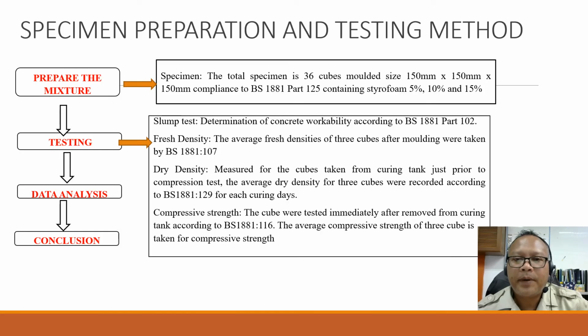Specimen preparation and testing method. For preparing the mixture, the total specimen is 36 cubes, molded at size 150 mm times 150 mm times 150 mm, in compliance with BS 1881 part 125, containing styrofoam 5%, 10%, and 15%.